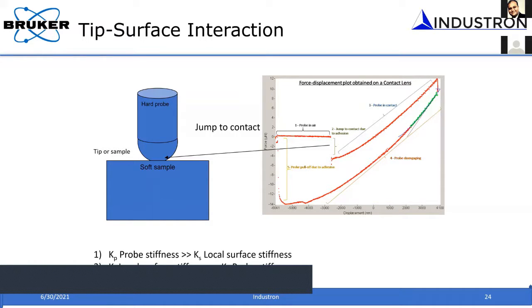We ignore the adhesion part, but here you can't do that because the adhesion forces are almost comparable to the forces that you are applying. And you're talking about the length scale, in this case from the point of contact to that maximum load, of about 5 micron. So even for small forces like 12 micronewton, the displacement range is about 5 micron. Normally for soft biomaterials, this is what happens.